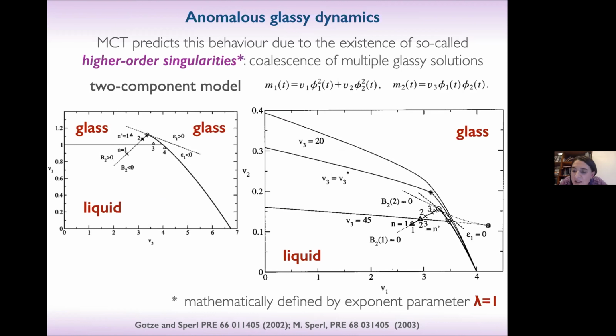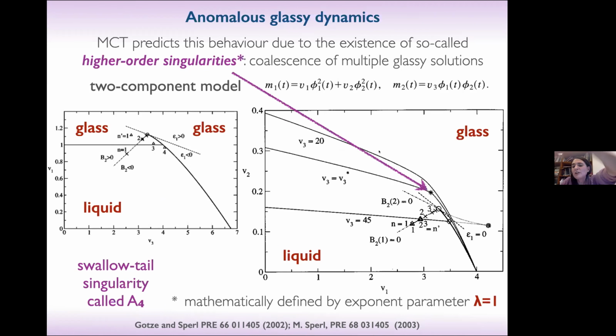And changing V3, what happens is that this glass line shrinks. So this line moves up, and you see that this line merges with this other at another critical point that is called A4. And it's called swallowtail singularity because of the shape. And then above, if you further increase V3, then you lose this, and you will have just a single glass. But interestingly now, coming back to the question of equilibrium, here you are in the liquid for this value of V3 until you arrive at the A4 singularity. And so, for example, you can do computer simulations going asymptotically close to this point and see if you find this anomalous dynamics, logarithmic dependence, for example, of the density autocorrelation function.